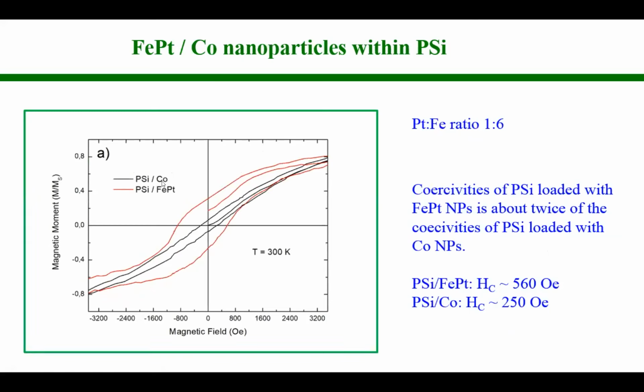With cobalt, this is the black curve, and with iron platinum, this is the red curve. And you see that the iron platinum composite offers a higher coercivity than the cobalt composite, and this is due to the more hard magnetic material.